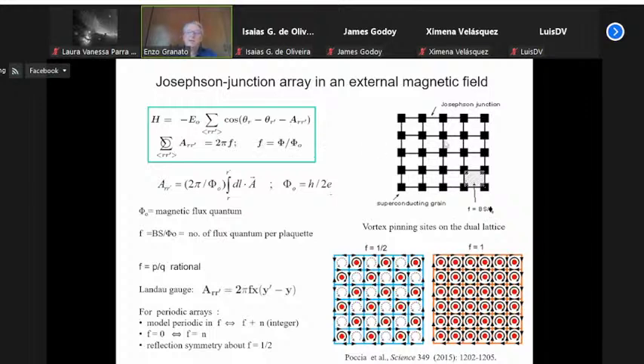Now, this model defines the system in the presence of a magnetic field, and the magnetic field creates additional vortices, whose number is proportional to the magnetic field, and there is a competition between this magnetic-field-generated vortex lattice and the pinning sites of the array. The center of each plaquette acts like a pinning site, and the vortex lattice created by the magnetic field can be commensurate or incommensurate with the pinning centers. That gives rise to different phase transitions. So, as I just said, f here is the number of flux quanta per plaquette, and is a dimensionless number. And the behavior of the system depends strongly on the value of f.